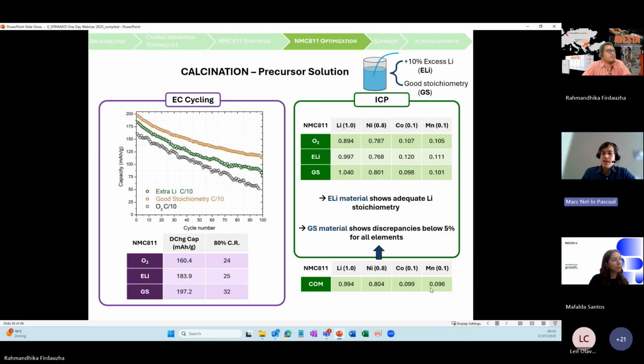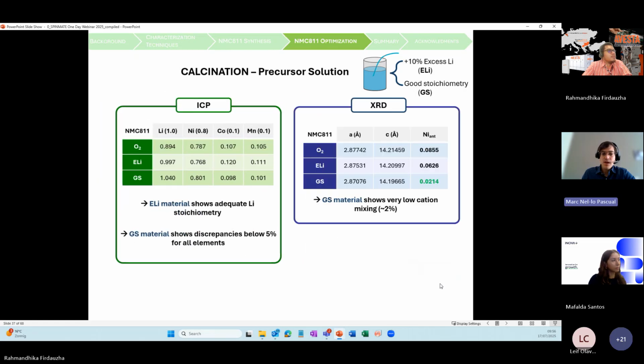We saw that in this case, the commercial sample also shows similar discrepancies below 5% for all of its elements. Lastly, if we also check the XRD information of these samples, we see that the excess lithium material shows an improved cation mixing value around 6%. That's pretty good. However, if we go for the good stoichiometry, now the cation mixing is very low. It's around 2%, which is in the order of commercial samples. Because we also did some XRD on the commercial sample, and we observed that this nickel anti-site effect is in the order of 2-3%, which is what is expected in a good performing NMC811 material. And if you look at the lattice parameters, both the good stoichiometry and the commercial sample show almost identical lattice parameters that are in the range of the NMC811 material.